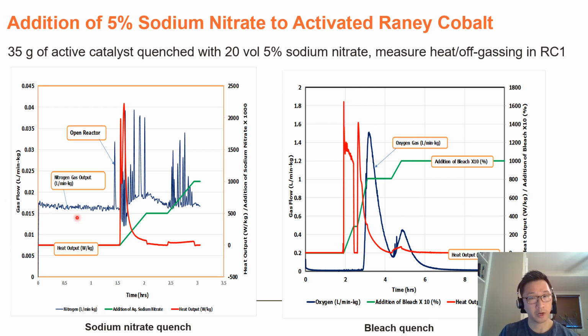Now when we compare the gas evolution, which is the blue traces here, when we start adding sodium nitrate, we do see some spiking here, but you notice the difference in scale of the y-axis, which measures the gas flow. For the sodium nitrate quench, we notice that it's nearly 50-fold less than the bleach quench. So this spiking that we see here is really not much more than baseline noise. There's very little gas evolution with the sodium nitrate quench.